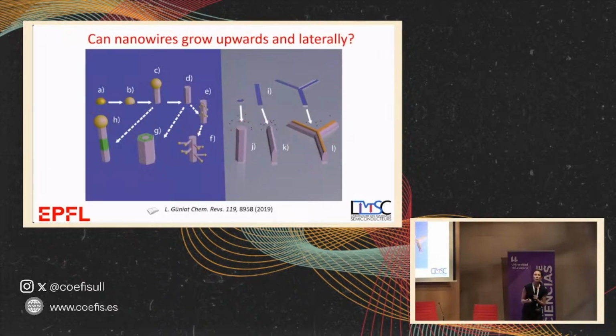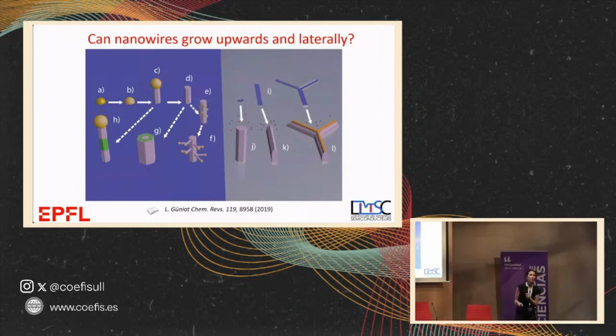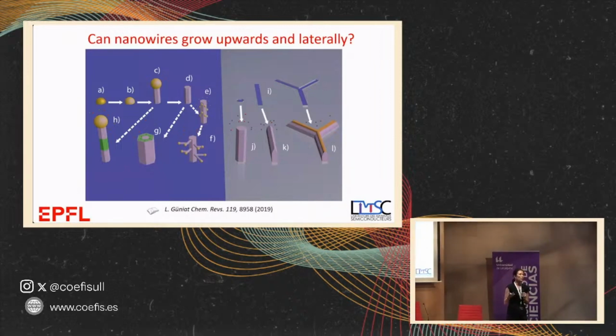So how can we do nanowires? You've seen we use a metal droplet to solidify material. This is a technique that has been used for many years. There's another way: we can use this anti-sticking surface, like an oxide, and then you can have nanowires that go up, but you can also try to think about other shapes. So you put the anti-sticking surface on a substrate, you open some slits, nanoscale, because we want to do nanoscale materials, and then you hope that you will have growth only there because the atoms don't stick everywhere else. And this allows you to make the drawings in principle you want.